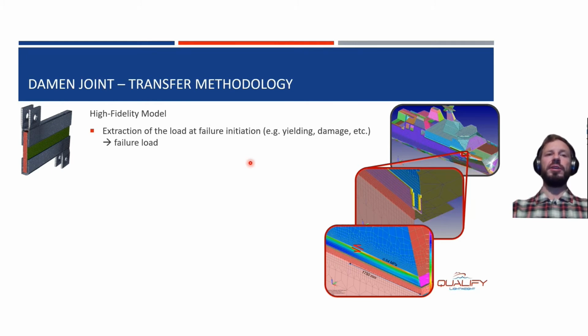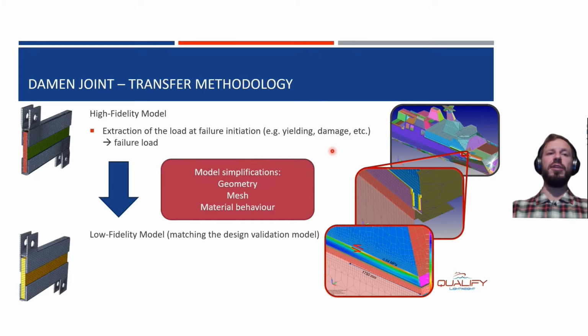Then from the high fidelity model, we create a low fidelity model through sub-model simplifications, such as the geometry. As you see, the flange is very simplified, represented here. We simplify the mesh, it's a coarse mesh with simple elements, and we simplify the material behavior. We don't have complex material behavior anymore, such as yielding, nonlinear behavior, fracture.